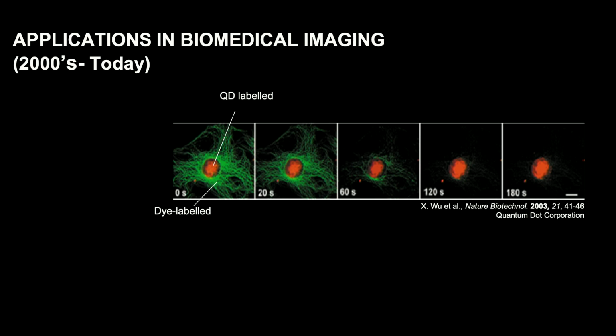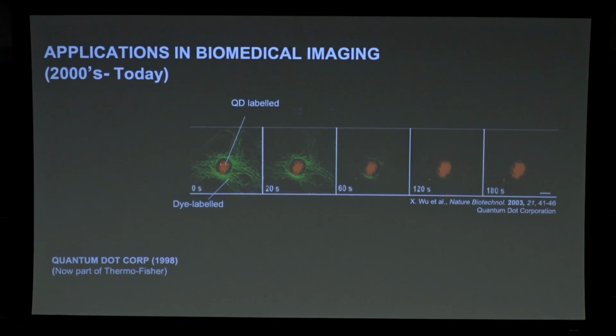Okay, application. So the synthesis happened in '93. People started making core shells in '96. And very quickly, the idea that you have this bright emitter that can absorb any blue light, independent of the size, etc. The first application that people thought about was in biomedical imaging. And there was a corporation that came out of that, Quantum Dot Corporation, a spin-off from MIT and Berkeley, founded by Paul Alivisatos and Shimon Weiss. And this is a slide that actually came from a paper from the company where they labeled the nucleus of this cell with quantum dots and the outside with a dye from what was then Molecular Probes. And I think Molecular Probes hated this slide so much that they ended up buying the company to get rid of it. Because it shows the dye sort of fading away and the quantum dots being really solid and not degrading with the light.